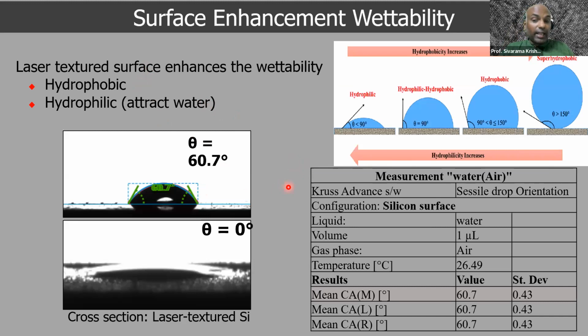So in this case, which was just a one-off study, we measured the contact angle after ablation, and we found that it is becoming more hydrophilic for the conditions that we have worked in. But for contact angles that are greater than 90 degrees, where the droplet becomes even more convex at the contact point, hydrophobicity starts to grow, and one even has superhydrophobicity.